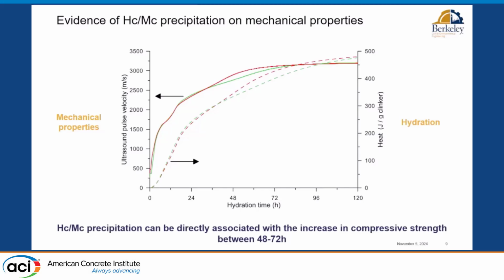So carboaluminates do contribute to strength. And actually, they explain how a cement with 50% clinker can catch up the strength of a type 1-2 between 3 and 7 days. And why between 3 and 7 days? Because you have to wait for this to happen. This basically closes the loop of how LC3 works, in a sense.